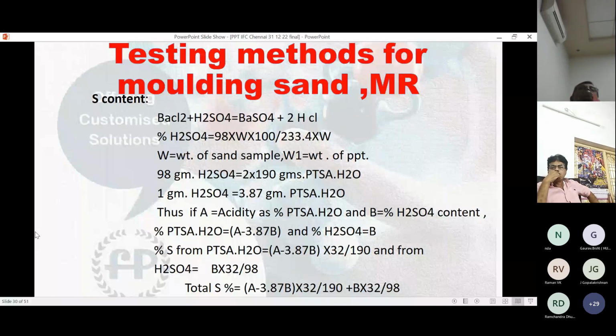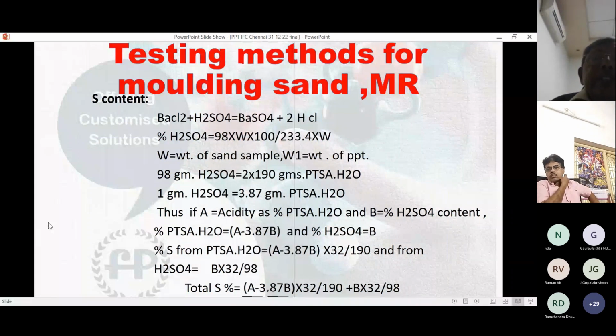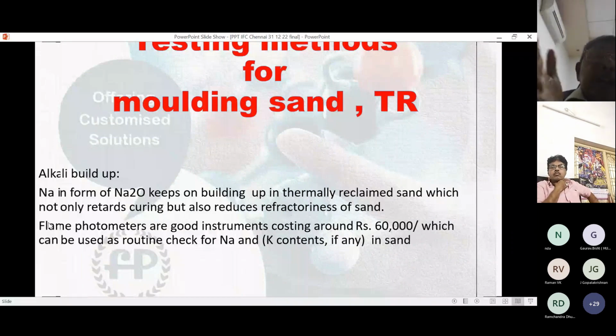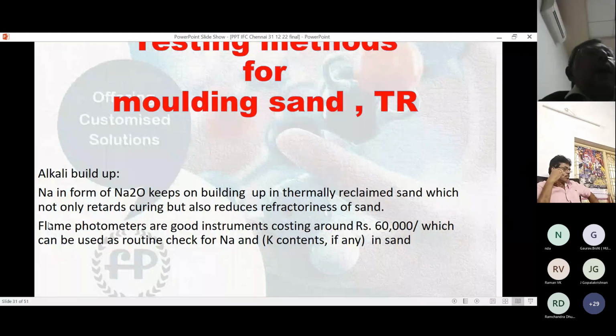With the figures, I have already given you how much percentage sulfur is contained in sulfuric acid as well as PTSA. These calculations, if you want, I'll forward to you. And these are very accurate tests. Recently we analyzed one sand, a thermal and mechanical reclaimed sand found in South Coimbatore. We found that alkali demand value is 13.53 milliliter 0.1 normal NaOH per 100 gram sand. Nitrogen is 0.104%, and sulfur is 0.0656%. And this test we have standardized by using known samples also.